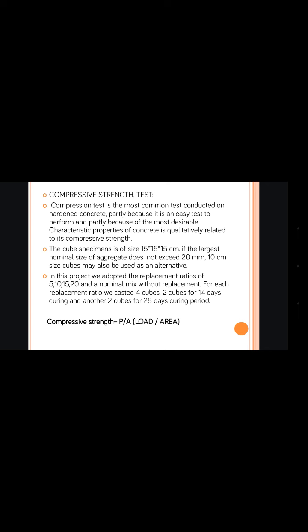After the casting of cubes, the most important test which comes now is the compressive strength test. The compression test is the most commonly conducted test on hardened concrete because it's a very easy test to perform and it's one of the most characteristic features of concrete. In this project, we adopted replacement ratios of 5, 10, 15, 20 percent and a standard cube, that is a nominal mix without replacement. For each replacement ratio, we casted 4 cubes: 2 cubes for 14 days curing and another 2 cubes for 28 days curing.